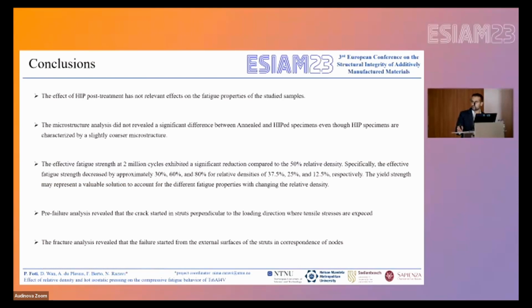To conclude this work, as we have seen, we have noticed no significant effect of the hot isostatic pressing post-treatment on the fatigue properties of the studied samples. The microstructural analysis did not reveal a significant difference between the annealed and HIPed specimens, even if the HIPed specimens are characterized by a slightly coarser microstructure.